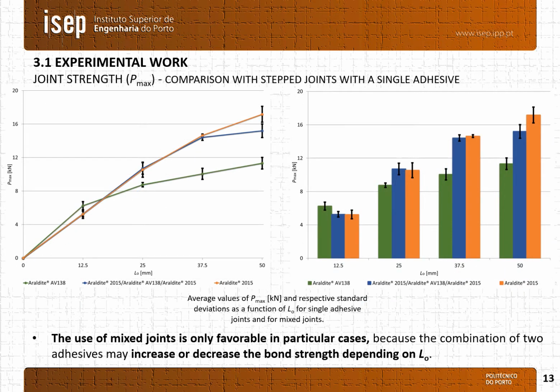Now comparing the dual adhesive with the single adhesive configuration, it is possible to observe that overall the best configuration is the joints with the single adhesive Araldite 2015. Also, it should be emphasized that the use of mixed joints is only favorable in particular cases, because the combination of two adhesives may increase or decrease the bond strength depending on the overlap length.